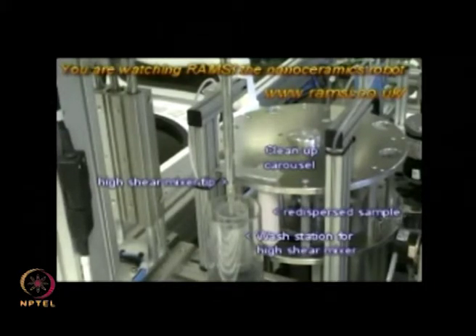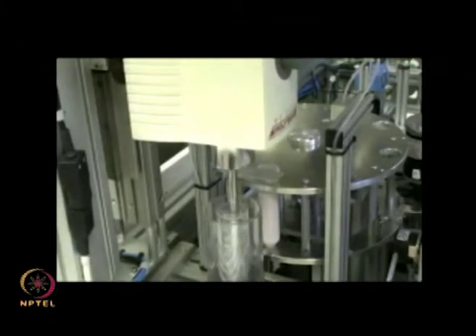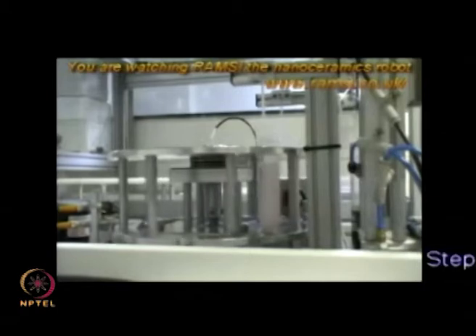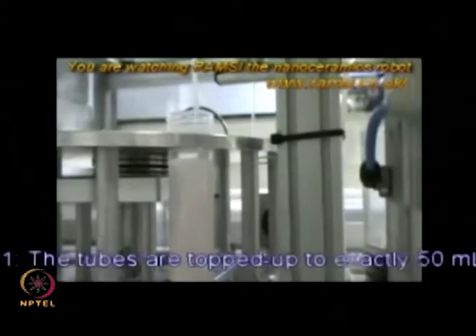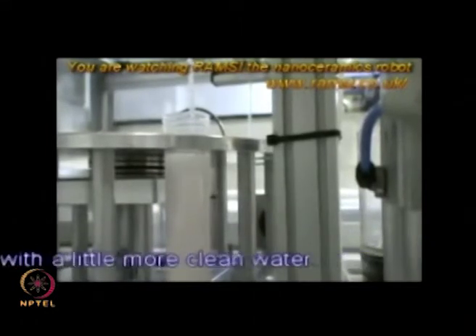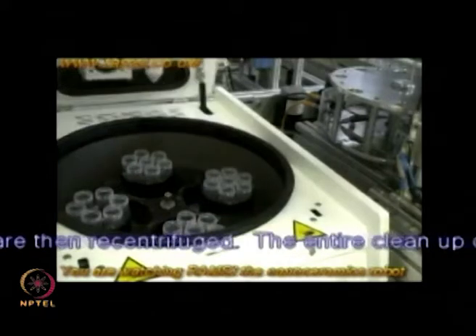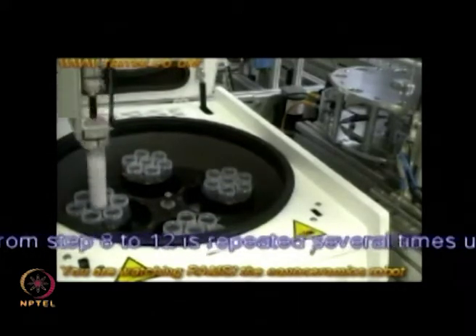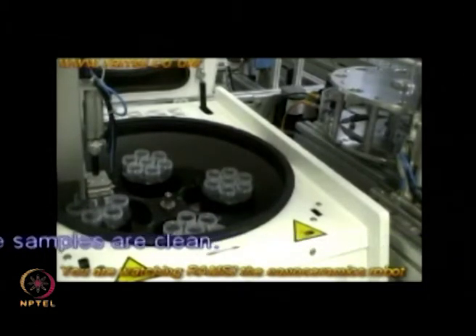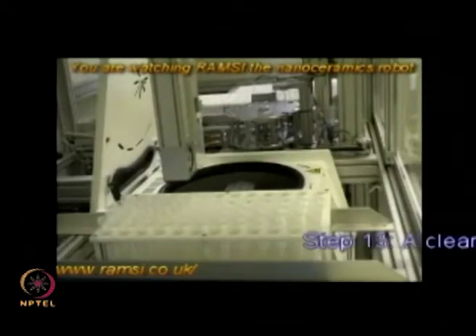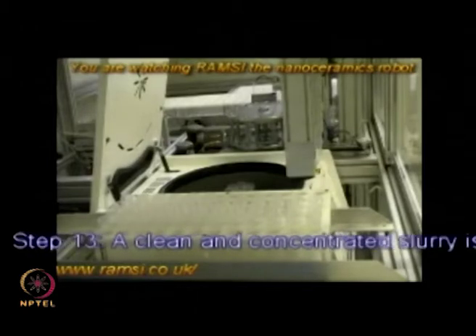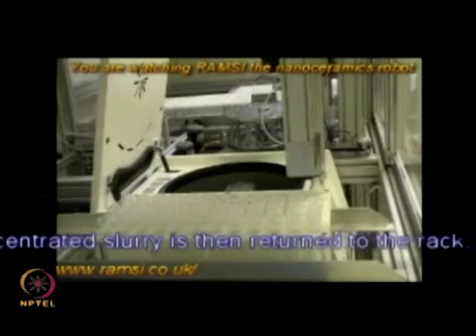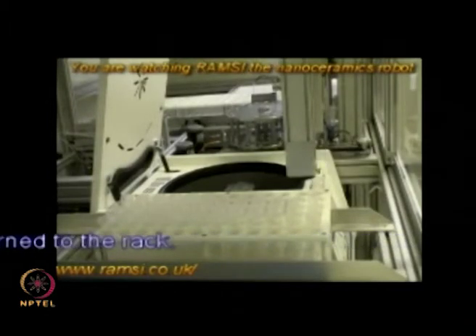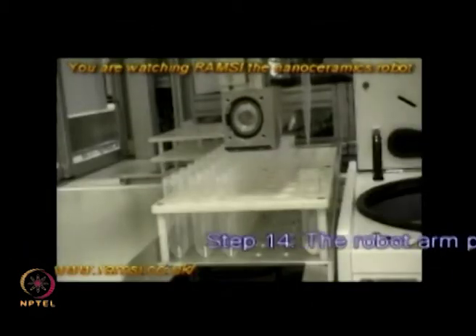This will be ultracentrifuged again, the liquid removed. Here they are topping it up. And as you can see, the samples are recentrifuged. The cycles are repeated several times until they are sure that the unreacted reactants are not there. At the final stage, they have got a clean slurry which is returned to the rack for further processing.